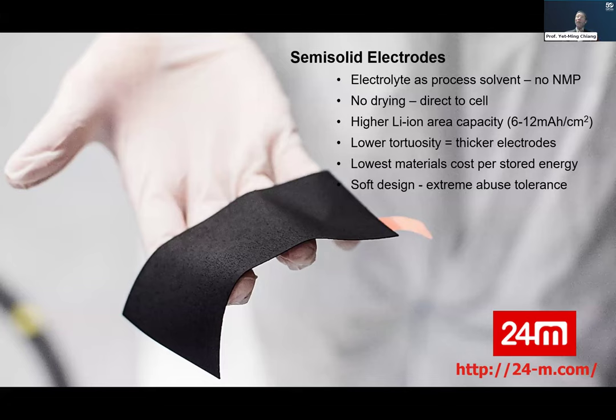And so in order to get around all of those steps, we created a different kind of electrode, and we ended up calling it a semi-solid electrode. And basically what it is, is an active material, carbon, electrolyte mixture with no binder, right? So no PVDF in this case. And what it allowed was that we could make an electrode that would be electrochemically active as fabricated and take it directly to a cell, no drying, right? And I've listed here a number of the advantages of doing it this way.